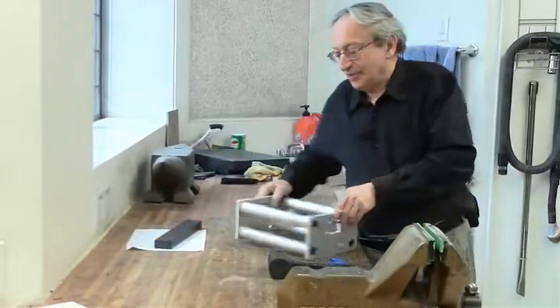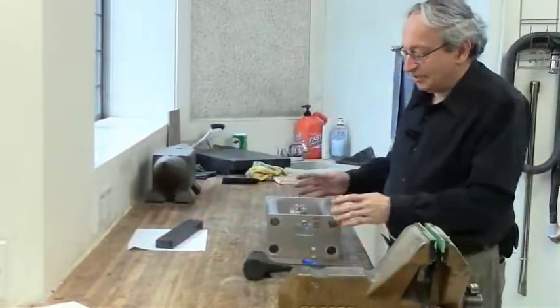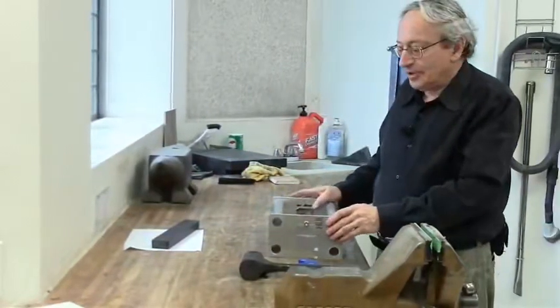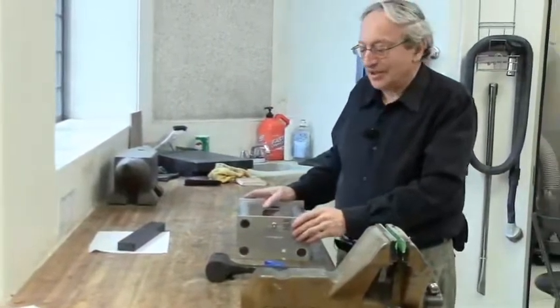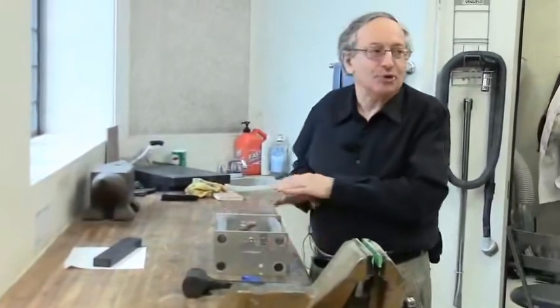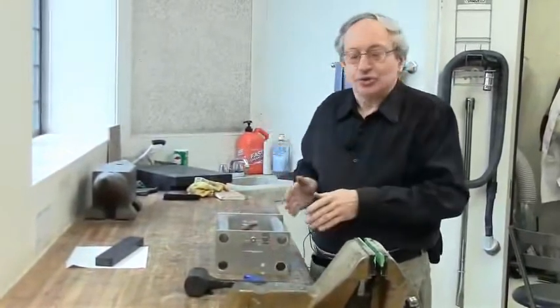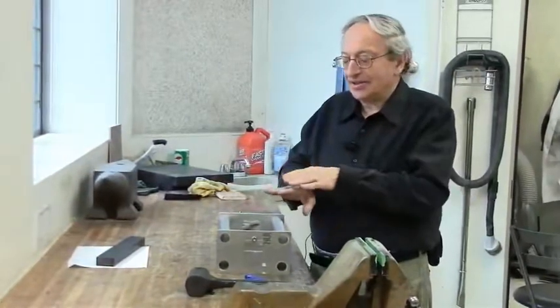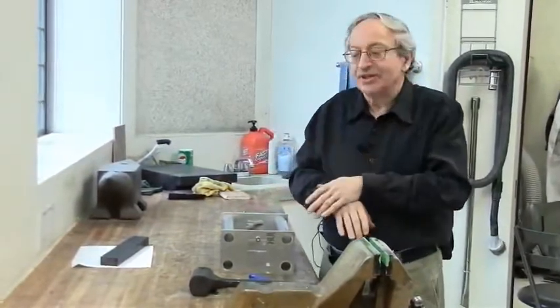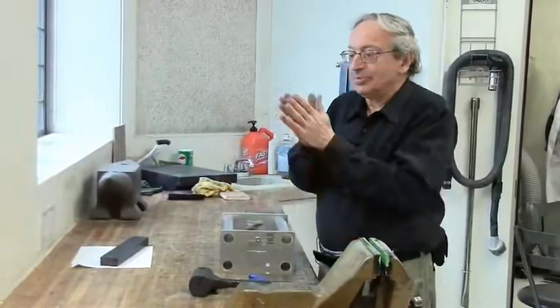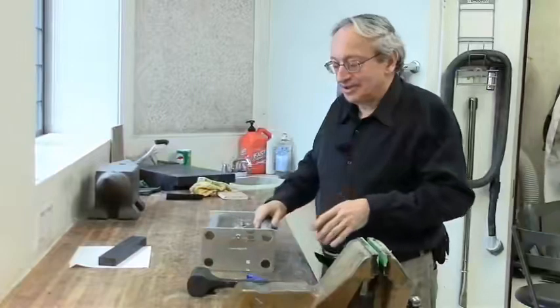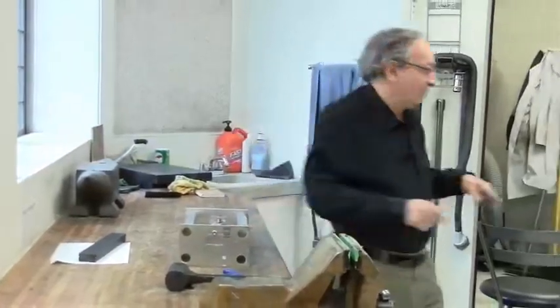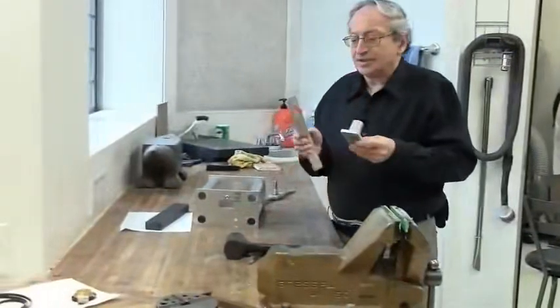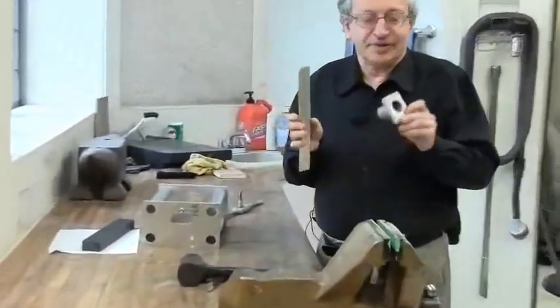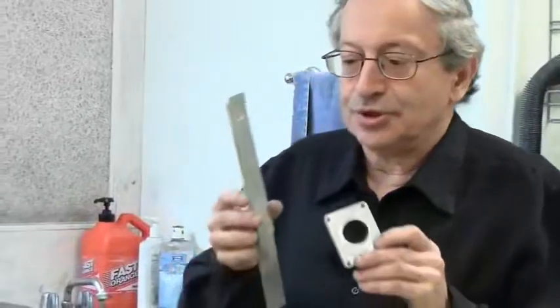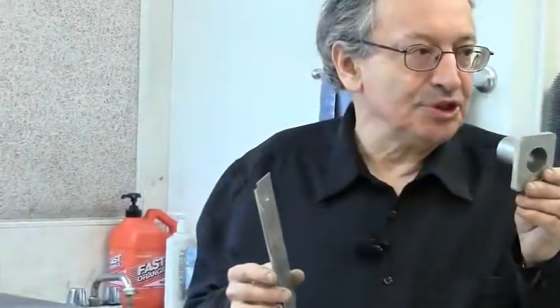So I want to explain something about adhesive joints. A proper adhesive joint should always be designed to work in shear mode, like this. Next best thing is designed in tension, which is much weaker, and never be designed to work in peel mode. And to demonstrate this, let's look at the samples we prepared earlier. These are the two samples we prepared earlier with 5-minute epoxy. One is for peel mode and one is for pure shear mode.